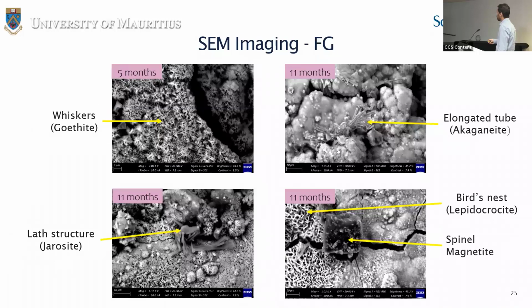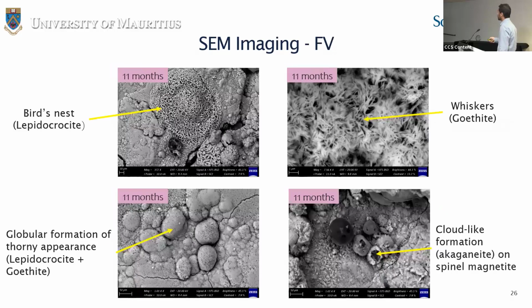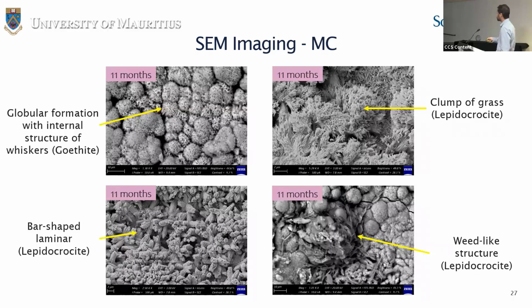At FG, elongated tubes of akaganeite and the structure of jarosite were observed. This is the site closest to the power station. At FV, a cloud-like formation on spinel magnetite was seen, and this cloud-like formation represents akaganeite. At the mid-island atmosphere, MC, two new forms of lepidocrocite were observed: clump of grass structure and weed-like structure. So these are the two new forms.